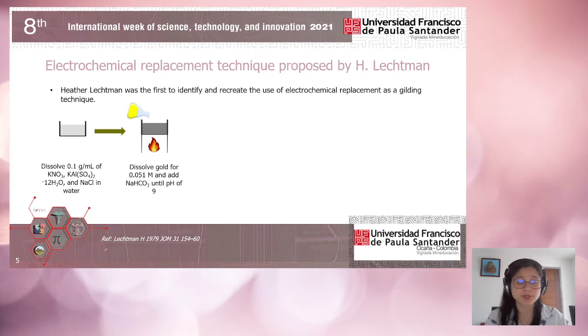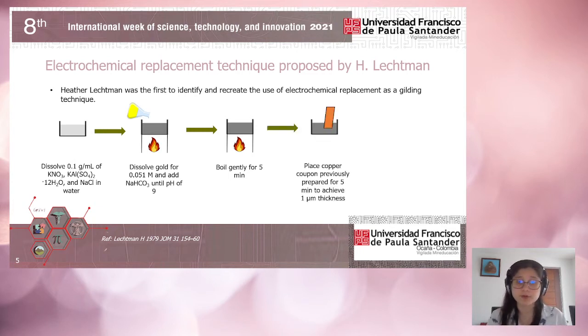Then she added the gold until a concentration of 0.051 molar, and also sodium bicarbonate until a pH of 9 was achieved. Then she boiled gently for 5 minutes and then immersed the copper coupon previously prepared for 5 minutes to achieve a thickness of 1 micrometer. Due to the weakness of the gold adhesion on the copper, an annealing process was required to increase this strength and to avoid the gold from falling from the copper coupon. That's why she described an annealing in atmospheric air at about 850 degrees Celsius for 5 to 7 seconds. This process created anodic regions, which means copper oxide, that were afterwards removed with the same salt solution.